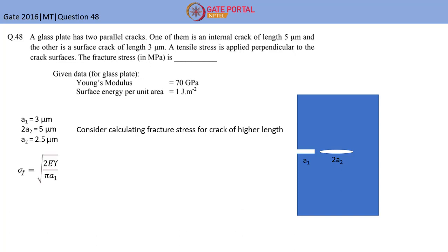Now you know that using Griffith's theory, the fracture stress is given by the square root of 2 times Young's modulus times surface energy per unit area, divided by pi times A1. We have considered A1 here. So when you put these values in the equation, you will get the value of 122 MPa. So this is the correct answer.